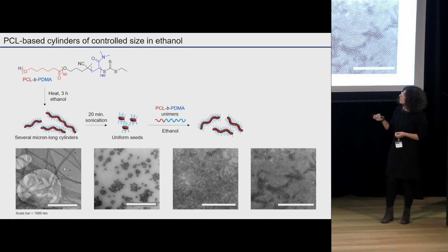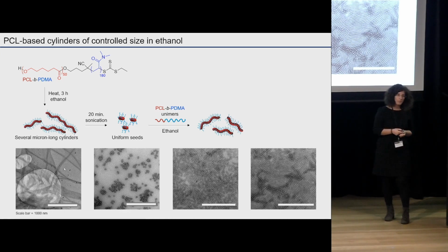And what you do with this polymer is to put it in ethanol for 3 hours, and you heat it up, and then you form very long structures, several micron long cylinders. So at this stage, what we have is a very good control over the nanoparticle morphology. We only get one type of structure, but it's not very good control in terms of size, because the cylinders range from 1 micron to 10 microns in length.